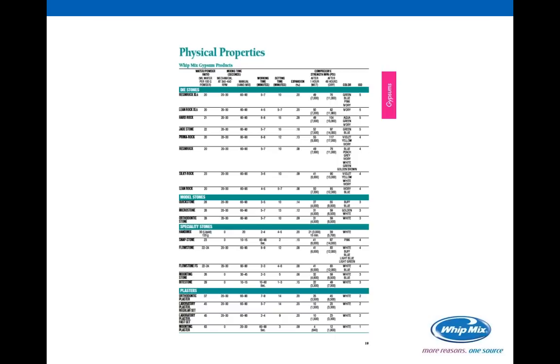That chart is divided up. If you can see on the left-hand side, you will have a listing of the Whip Mix die stones broken into those groups: die stones, model stones, specialty stones, and plasters. And then we will give you the other physical properties that are reported. That would be your water powder ratio next, the amount of mechanical mixing time that you should use if you're going to do that, also a little bit of hand mixing time. You're going to have working time that's in there, the setting time for each stone,